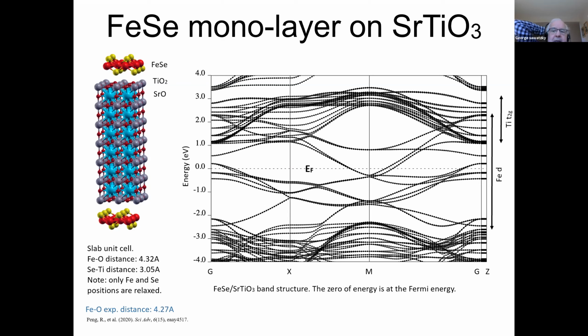An iron selenide monolayer on strontium titanate, as I just showed you, should be a semiconductor, okay, with a small gap. And the bands at gamma are all below the Fermi surface in the experiment, and at the M point are above the Fermi energy. And what you get in density functional theory is that those are degenerate. In fact, density functional theory has a big problem with all of these, okay? So this is done with iron selenide on strontium titanate, with the assumed lattice constant of strontium titanate.